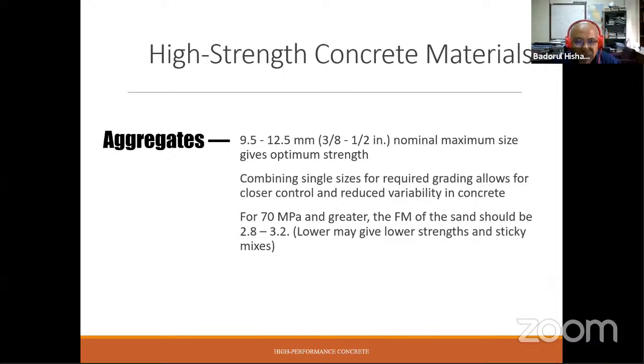And combining the single size of required grading allows for closer control and reduces variability in concrete. For 70 megapascal and above, the fineness modulus of the sand should be between 2.6 to 3.2. Here in Malaysia, we have about 2.65. Lower may give lower strength and sticky mixes because you need a lot of water for wetting all these aggregates.